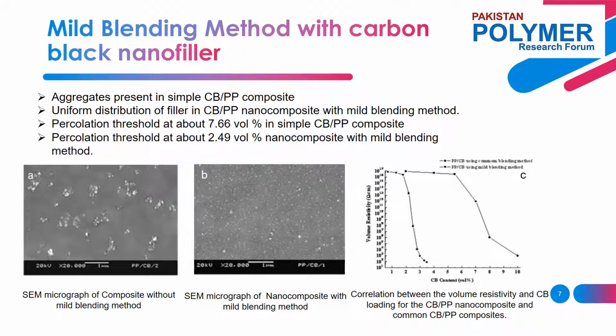In order to observe the impact of the mild blending method on the dispersion of filler, the carbon black and polypropylene nanocomposite and the simple composite of carbon black and polypropylene were analyzed using SEM analysis. The SEM micrograph of the common carbon black and polypropylene composite, as shown in figure A, showed that most particles were aggregated together and the aggregates were detached from each other.